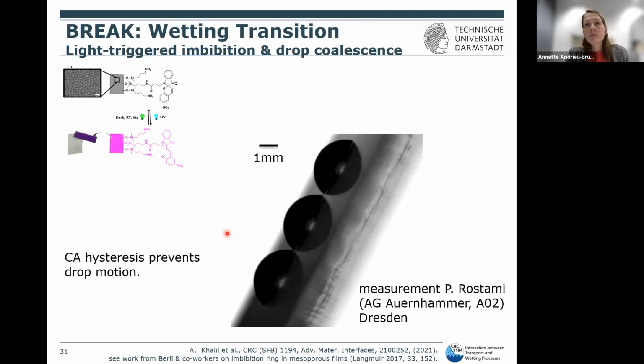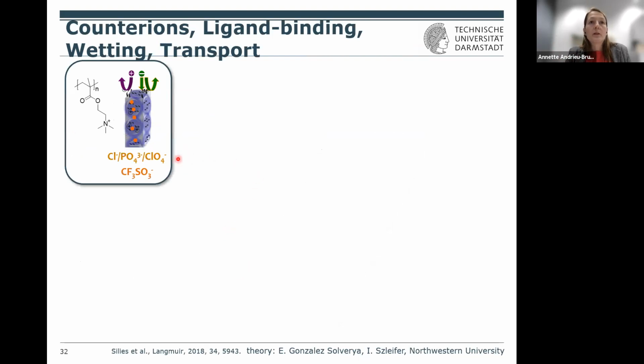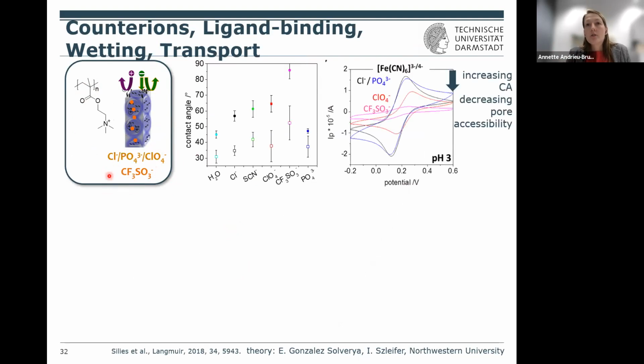fluid imbibition. And to close this part of wetability control, I'd like just to draw your attention to the fact that if you have polymers in these pores, even ions can introduce wetability changes. That has a different reason, of course, that has to do with the polymer conformation, but that's as well pretty interesting if you think about separation, because in real separation, you will not just have your model ion present, but a mixture of ions. And what you see here is that, again, this polymer, and you just add different ions to the solution you are measuring contact angle with, or you immerse your substrate into these ionic solutions, and you see drastic contact angle changes up to hydrophobic pores.